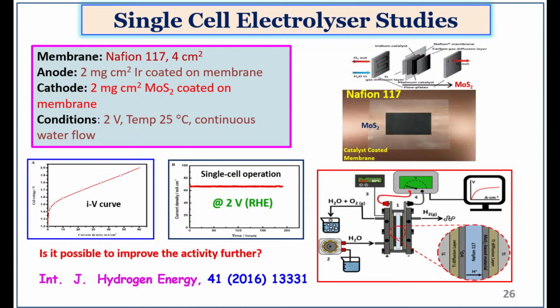So after that, we went for the single cell electrolyzer studies, because anything you produce in a laboratory should hold up in system studies. Okay. So we handed over the material to a nearby laboratory, where they did the single cell studies, employing Nafion 117 in a 4 centimeter squared area. It's a little bit large scale. The anode is composed of 2 milligrams per centimeter squared of iridium coated on the membrane. So the anode is always a very active material for oxygen evolution. And the cathode is our MoS2 at 2 milligrams per centimeter squared, which is directly coated on the membrane.